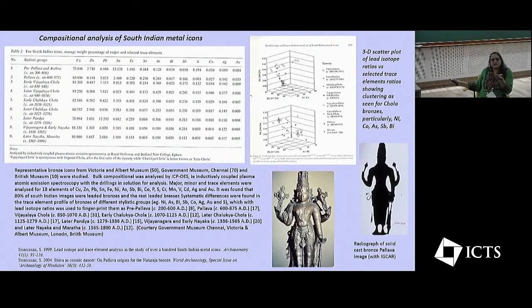And in fact, if you ask him to make a Panchaloha icon, he can just buy a very small amount from the goldsmith and add it, like a pinch, with a spoon, at the final stage of the casting. But it won't reflect in the composition more than 1%, because these are very heavy metal castings, at least 50 kg to 200 kg. So even if you add 1 tola or something, it won't be detected in any significant way above 1%. So that was explaining why I was not getting a clustering with the gold-silver composition.